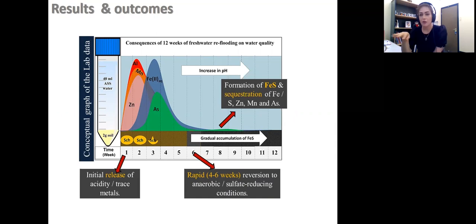But at the same time, if you want to remediate these soils and sediment, we can see a rapid reversion of the anaerobic conditions and the sulfate reducing conditions to occur, and for the pH to increase. And it takes about 4 to 6 weeks for our samples to recover. So it was an interesting discovery with these two experiments.